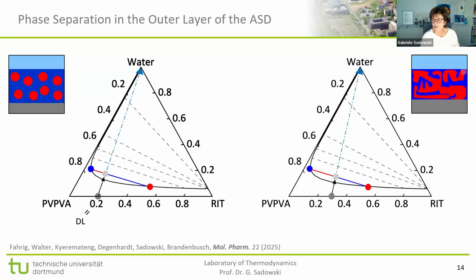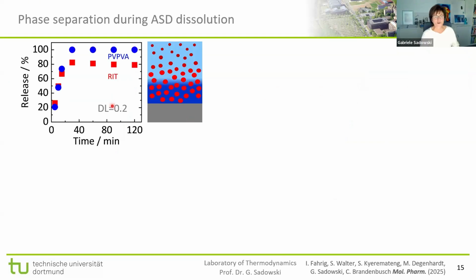We have now a system that looks more like this. We have domains really of both the Ritonavir-rich phase, which is the red one, and of the polymer phase. And we should not forget that the red one is the hydrophobic, so this will not like to dissolve in water where the polymer would. And so due to these different morphologies, we observe different dissolution behavior.